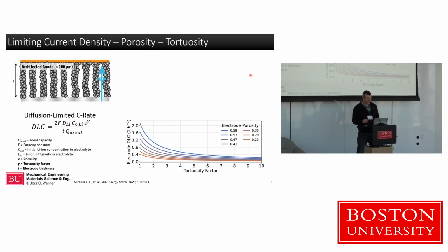Now, if we look at this equation here and we put some numbers to it that are typical, again, tortuosity factors from straight, meaning 1 to 8, 9, or 10, which is often reported for just random particle agglomerates, and we look at different thicknesses. So here we're plotting it for a thickness of 200 microns, which would be a fairly thick electrode, not what you have in your batteries or cars these days. And we look at different porosities listed here from 23%, which is a very low porosity. That's what we often have in high-energy batteries, up to like 50 and above %. You barely see that ever. It's too much porosity, but we can plot it.